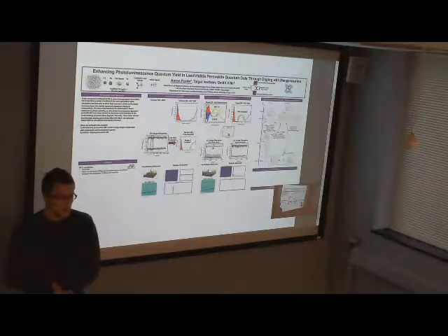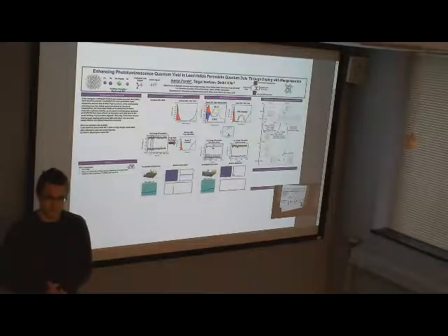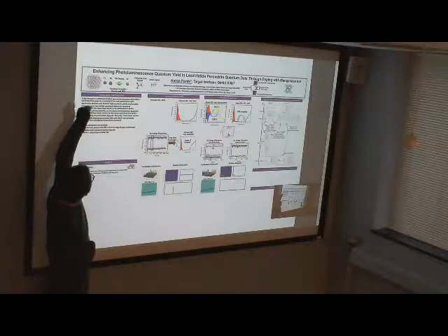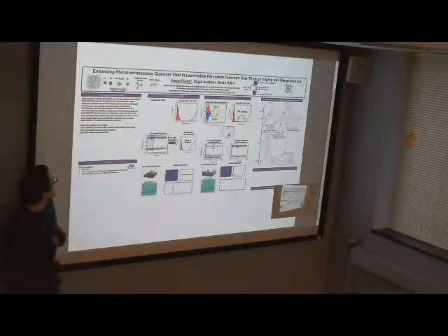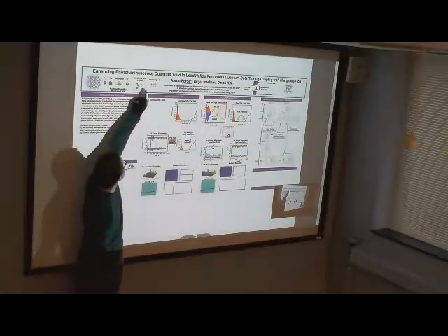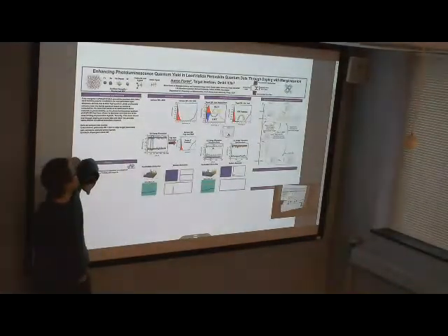And then a popular method throughout the history of quantum dots to try to get stable emission out of them is to dope them with metal or transition metal dopants like manganese 2+, which is what we did for our models here. So there's an image of the perovskite quantum dot in the upper top left, where the outside is the passivating ligands of the carboxylic acid and amine ligand groups, and we chose those groups because that's what's used experimentally.